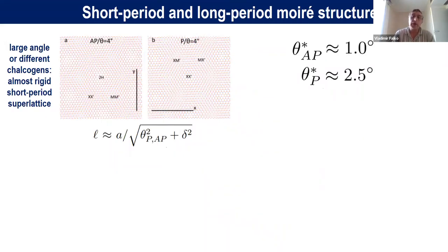We can look at larger angles of misalignment and smaller angles of misalignment. And what we find is that for these TMDs systematically, for anti-parallel orientation of the unit cells, if the angles are more than 1 degree, and for parallel, if they're more than 2.5 degrees, then there is very little reconstruction of the lattice taking place.